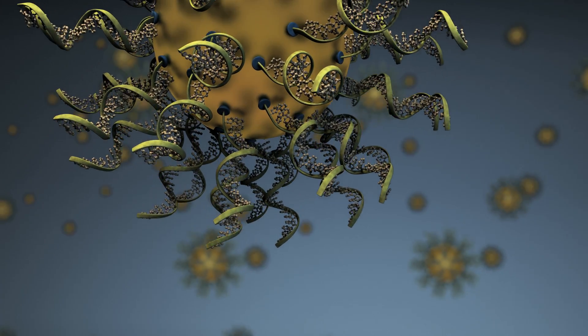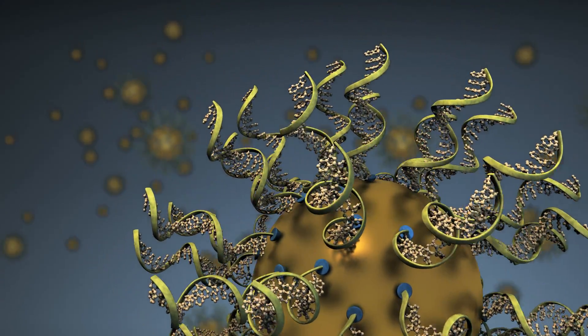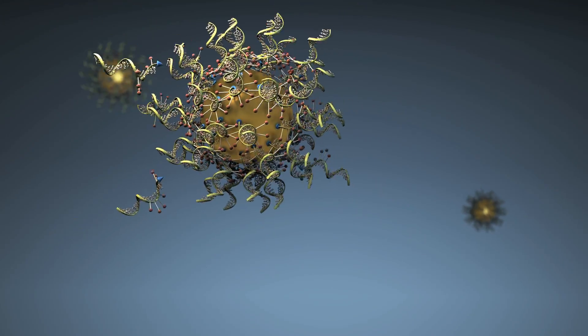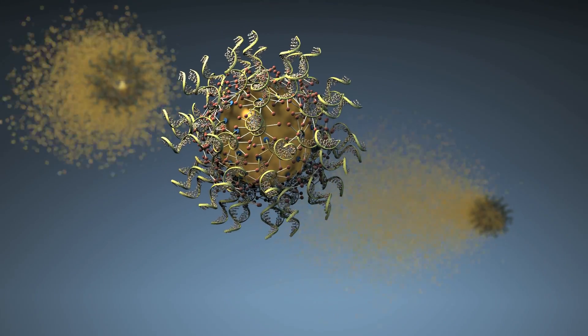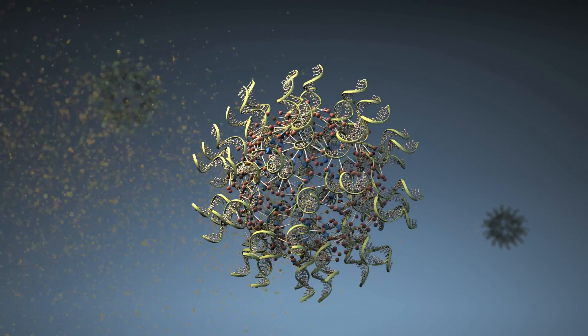All of these unique properties stem from the densely packed spherical arrangements of nucleic acids that define the SNA. One can even dissolve the nanoparticle scaffold to create a coreless or hollow form of SNA, which exhibits many of the hallmark properties of the original nanoparticle conjugate.